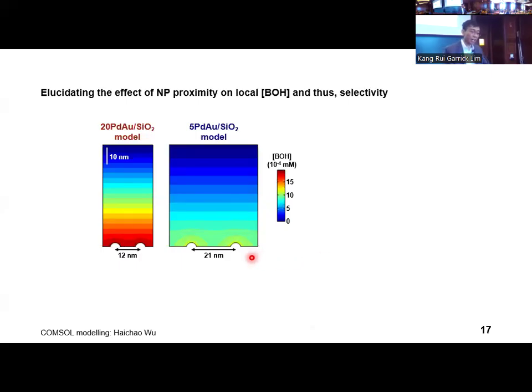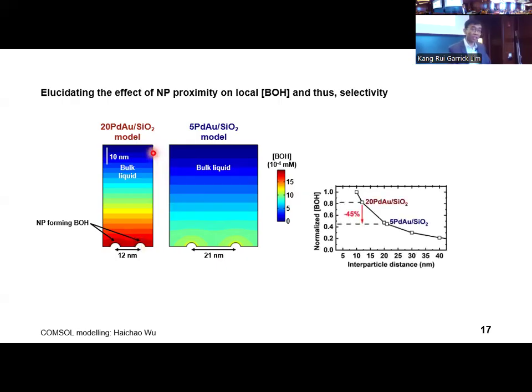To evaluate how the nanoparticle proximity affects the local benzyl alcohol concentration profile and subsequently the selectivity, we used the interparticle distance data and simulated the local benzyl alcohol concentration profile around the nanoparticles. In this model, nanoparticles act as point sources to produce benzyl alcohol, which diffuses into the bulk liquid. The benzyl alcohol concentration is visualized using a color scale bar, with red indicating a higher concentration and blue indicating a lower concentration. The trend of the local benzyl alcohol concentration as a function of interparticle distance is summarized here.